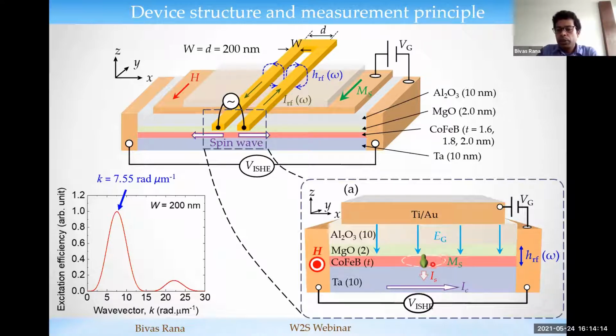Then when we excite the ferromagnetic resonance, that carries spin angular momentum. And the pumping of the spin current basically means the transfer of the spin angular momentum to the conduction electron spin. That means the up spins are going like this, or let's say the down spins going like this. I have some echo problem. Then it is converted to a charge current by the inverse spin Hall effect. I hope that answers the question.